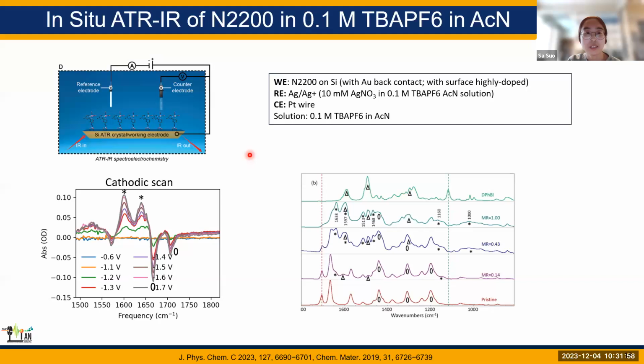We also did the in situ ATR IR spectra of the N2200. Here we deposit N2200 on this silicon ATR crystal and do in situ ATR IR measurement under working condition. Here are the spectra showing the cathodic scan. After -1.2 volts, we can see that there is growth. This is also the difference absorption spectra.